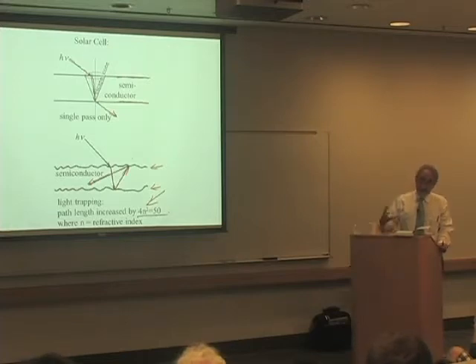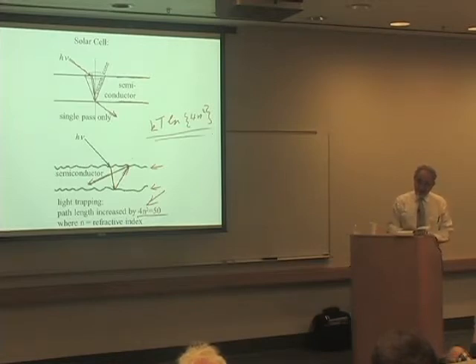and because you would be concentrating the same number of carriers in a smaller volume, you actually, and this is one that I probably should have published more, it's kT log of 4n squared. You actually get an increase of voltage of kT log of 4n squared, which is at the operating point. So it's a big increase in voltage. It's about 4 kT. So huge benefits accrue when you recognize that it's possible to trap the light in the semiconductor.